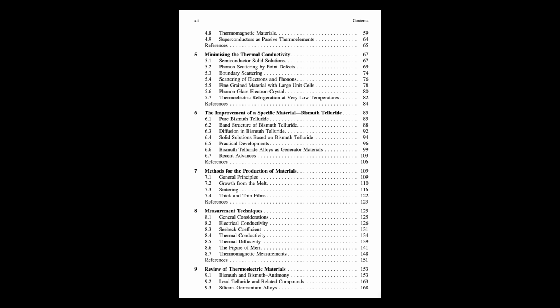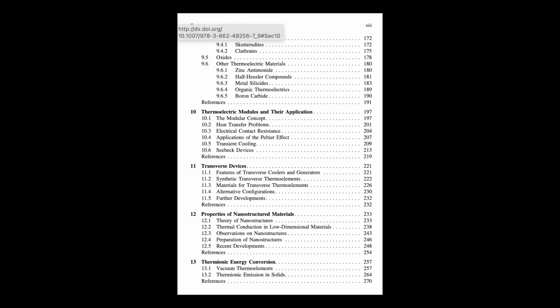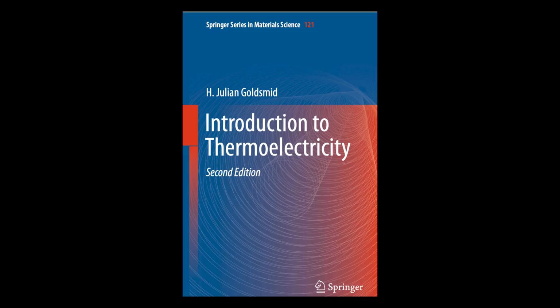Okay, let's shift to how we actually make these materials and measure their properties, which can be tricky. Starting with growth from the melt. Right, growing from a molten state is pretty common. Simplest way, melt the elements, let it freeze. But for better control, especially getting impurities distributed evenly and aligning the crystal structure, which matters a lot for anisotropic materials like Bi-Te, you use directional freezing. The Bridgman method is a classic. You put the melt in a sealed tube, often quartz, and slowly pull it through a furnace with a sharp temperature change. It starts freezing at one end, and the solid grows progressively along the tube. Gives you better crystals, better alignment.